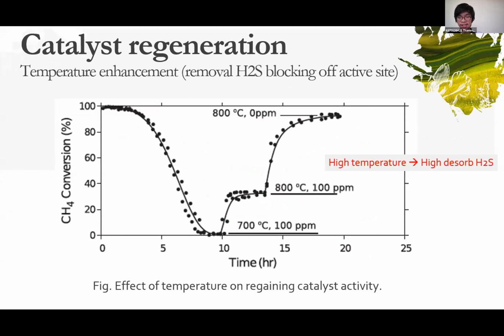The second method is temperature enhancement. The results show the catalyst is almost completely deactivated in the presence of 100 ppm of hydrogen sulfide at 700 degrees Celsius, and the catalyst begins to recover activity at 800 degrees Celsius and stabilizes at 30%. Finally, the hydrogen sulfide is removed from the feed gas at 800 degrees Celsius, and the methane conversion stabilizes at 95%. The results show that increasing the temperature can be used well for regeneration of the poisoned catalyst, and indicate that increasing temperature can improve the reversibility of the adsorption of sulfur.